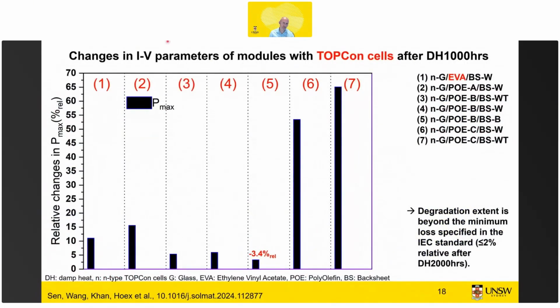But if we then look at the performance after this 1,000 hours of temp heat testing, we see that one of the bills of materials resulted in a 65% loss. And this paper, which we published in 2024, really created a big stir in the industry, that really opened the eyes of many module manufacturers who do not make their own cells. So everybody who is vertically integrated knew that TOPCon cells were very sensitive to certain encapsulants, or that the metallization by itself was actually very sensitive. So they were fully aware of this, and this was not shipped in any product. But if you're not aware of this as a module manufacturer, you might be buying cells that have this sensitivity. And if you pick the wrong POE, your modules will degrade very, very quickly.